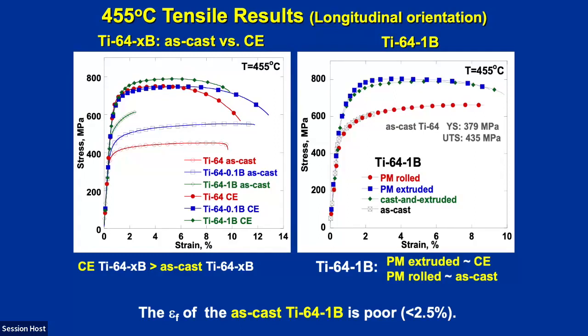And what we see at the top here is that we can get cast and extruded with 1 boron to have strengths on the order of 800 megapascals at 455 degrees C. And it's relatively ductile, 10% elongation. If we look at just the cast and extruded without boron, we get a slightly lower strength. With 0.1 boron, we gain a little bit more strength.